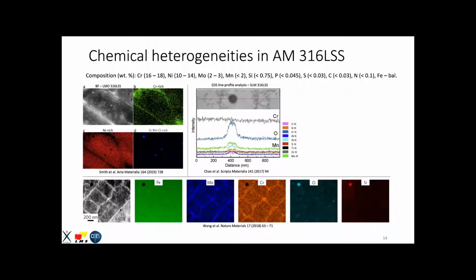Okay. Now, since we were focusing on the chemical heterogeneities, the best way to study them is to characterize them with EDS. So here are many different EDS studies that are done, and all of them agree that the microsegregations are molybdenum chromium rich cell walls, and the precipitates are all oxides, manganese silicon oxides. So we were expecting to see that.